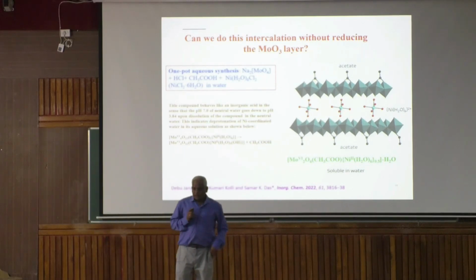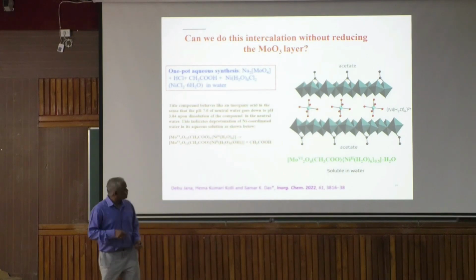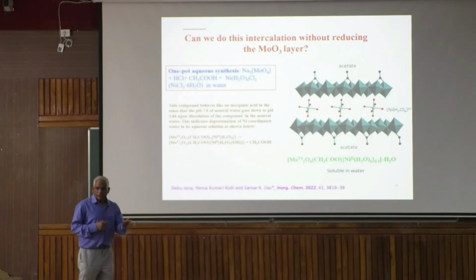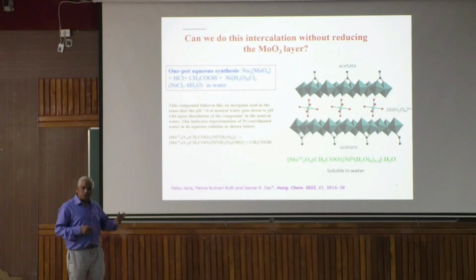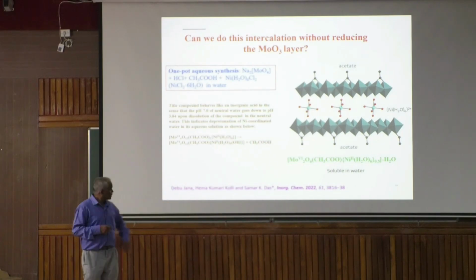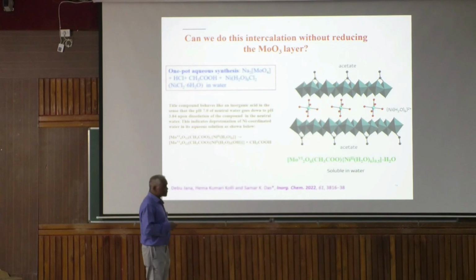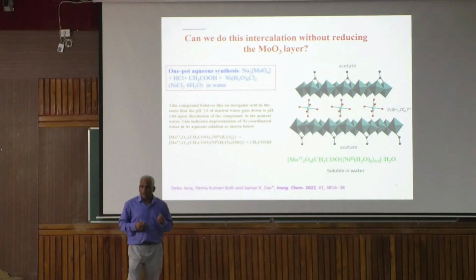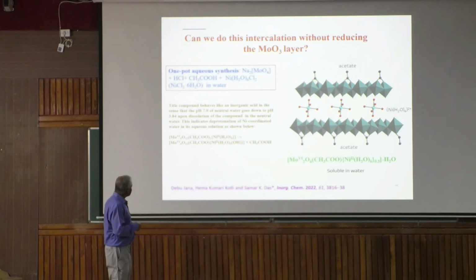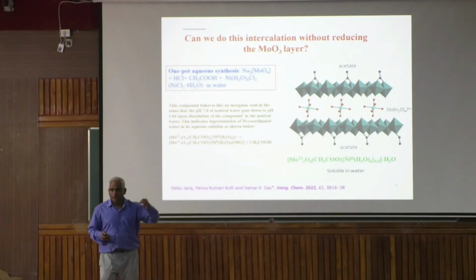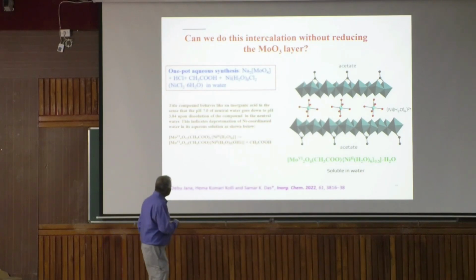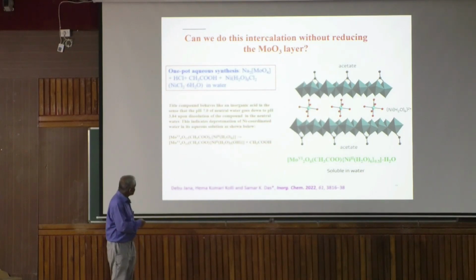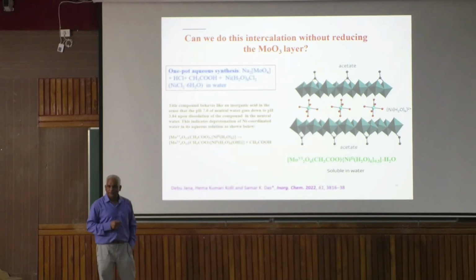Not only that, if you dissolve the compound in water, pH becomes 3.8. Water pH 7, no? pH becomes 3.8. That means the compound is an inorganic acid. Isn't it? Why is it happening? Definitely, when you dissolve, some proton comes out. If proton has to come out, what is the possible thing? Definitely some deprotonation of the water. As inorganic chemists, we did acid-base titration, and we found out that one of the waters actually gets deprotonated and it formed like that. So in the solution, the compound will give nickel penta-aqua, 1 OH. Okay. So this compound formed, and that's why it is acidic in nature.